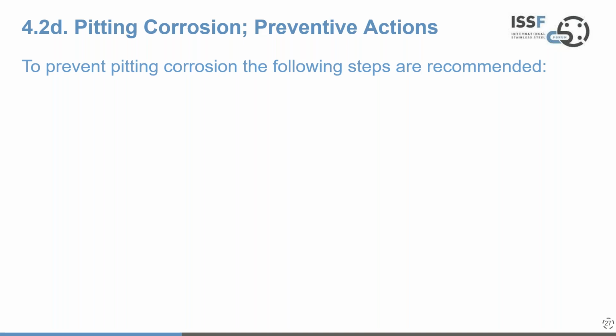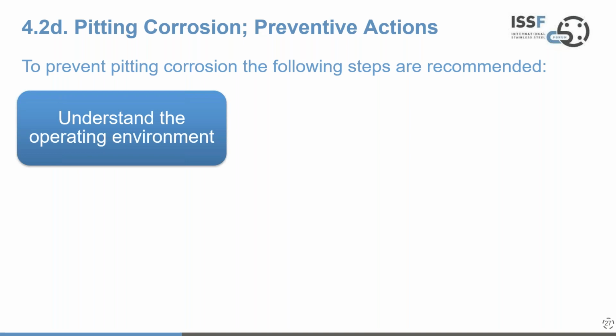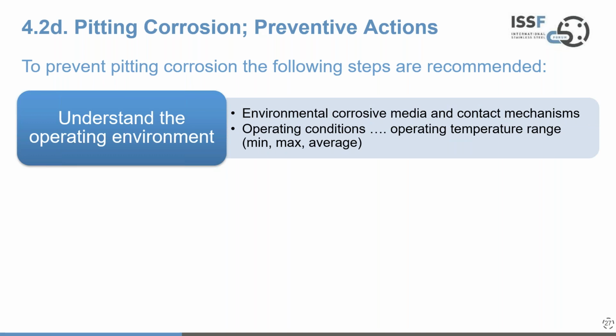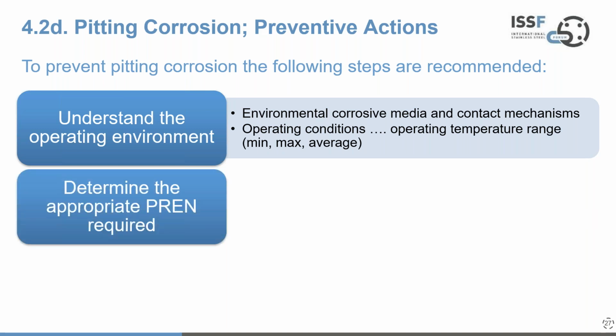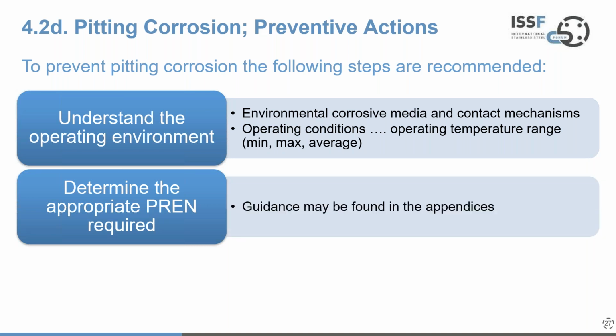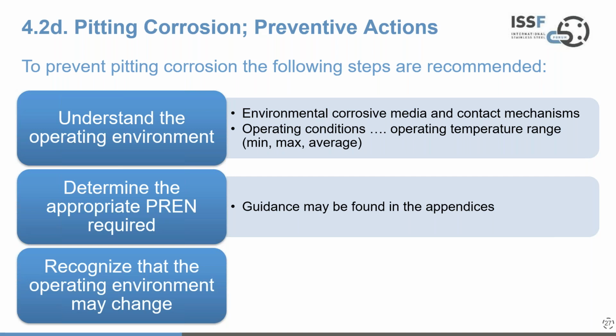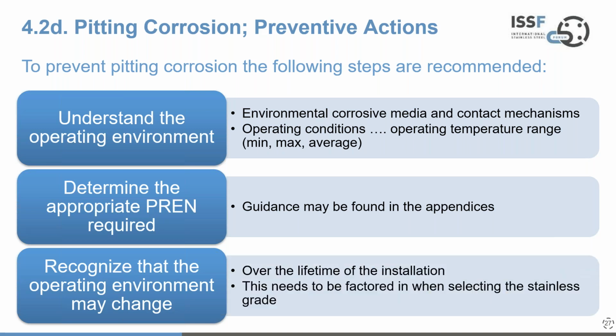So how do we prevent pitting corrosion? So first and foremost, we need to understand the environment, because without that, we don't have a clue what to do. So we need to think about corrosive media, contact mechanisms, and the operating conditions, particularly the temperature range, min, max, and average. We need to know what's going on there. We can then start to determine the appropriate pitting resistance equivalent number that is required. So these elements are connected: understanding the environment, determine the pitting resistance equivalent number. As I've said, guidance to this is found in the appendices, but also we have to recognize that the operating environment may well change. It's important that we deal with that, and we've got to think over the lifetime, and that's not always easy, but we have to take some good judgments into account there.